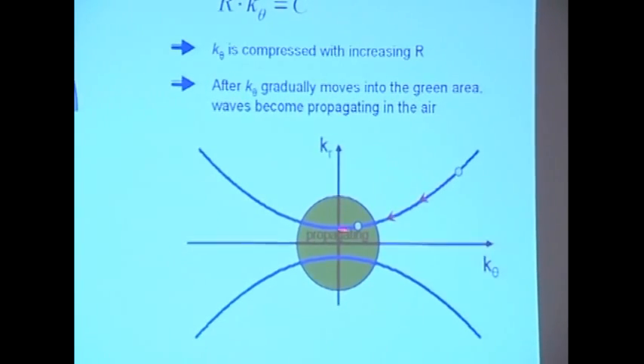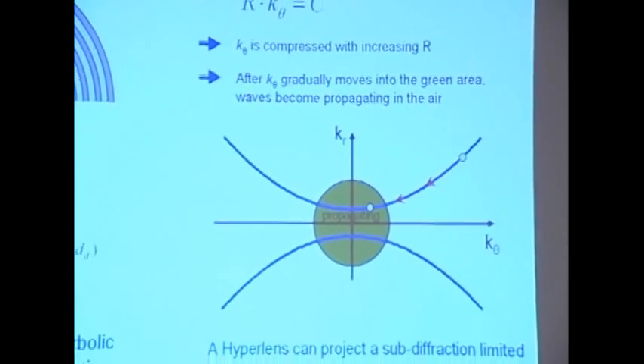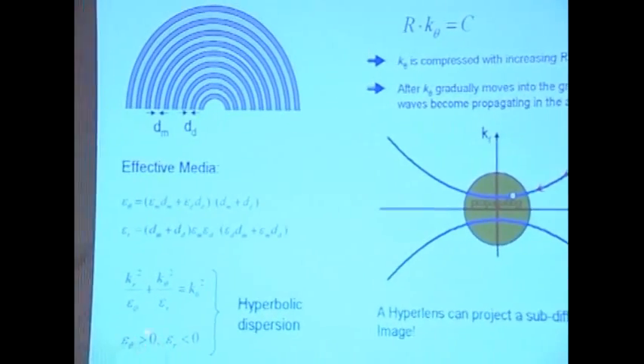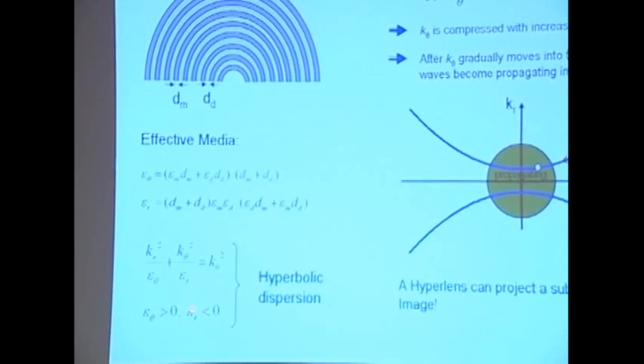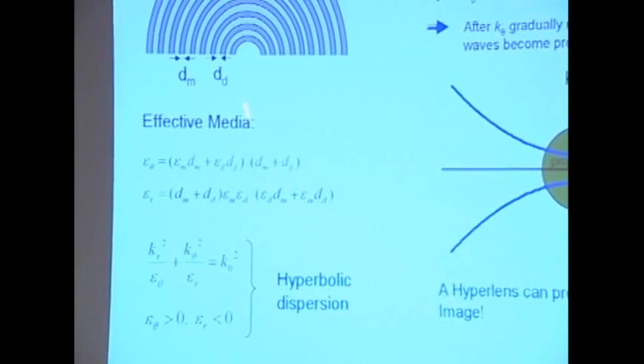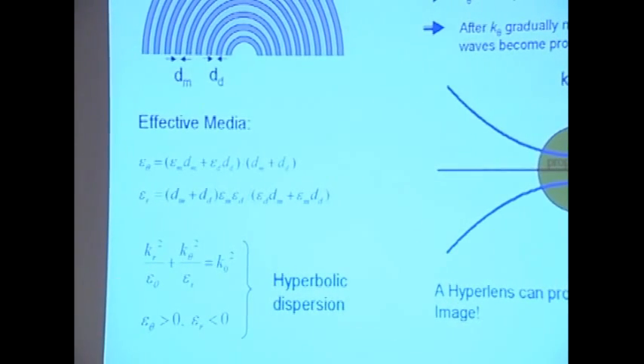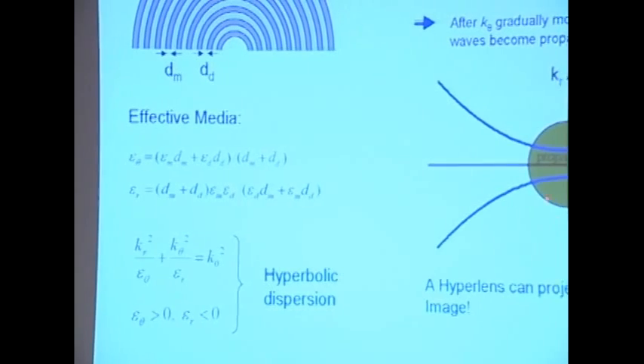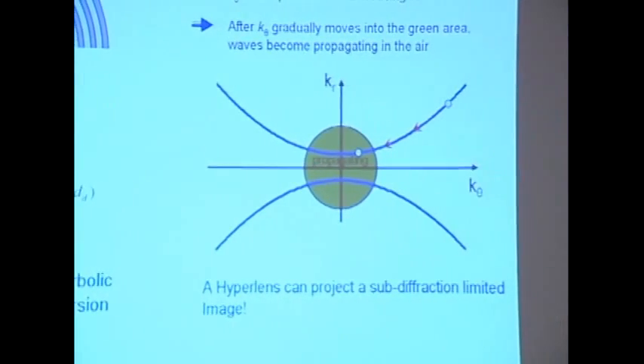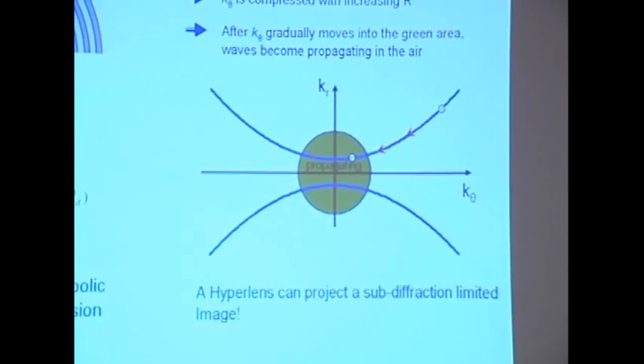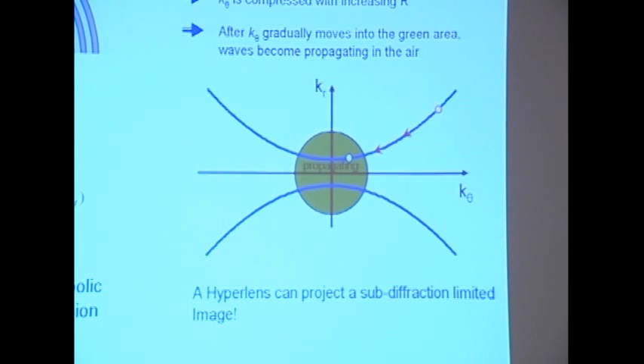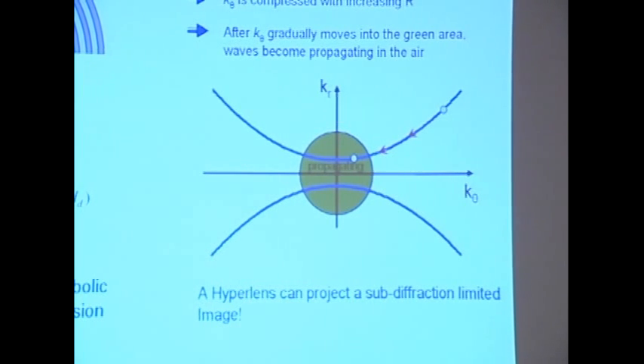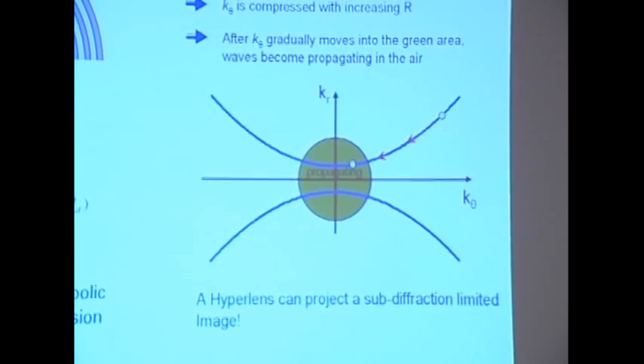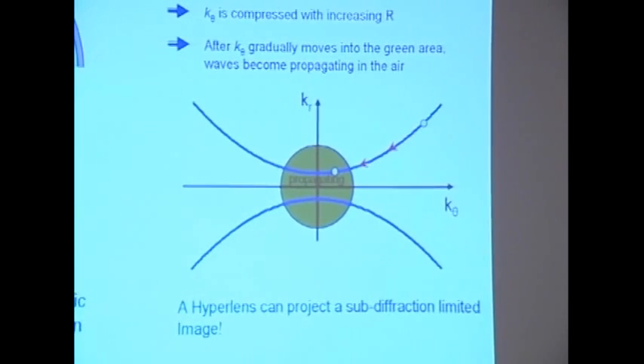What happens is you can engineer it so that one of the electrical permittivities is larger than 0, and the other, along the R direction, is negative, or vice versa. Such that waves with a very large K vector, once they get into this media, become propagating. As long as they are on the green curve, they become propagating. And as they propagate out, the tangential photon momentum has to be conserved. So it's like figure skating.